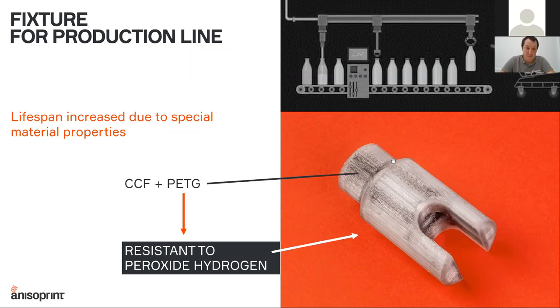For example, polyamides will start dissolving in hydrogen peroxide, and PETG is very highly resistant to this chemistry. By using PETG as a matrix together with a reinforcement to make the part strong and durable, the requirements are satisfied, and the part can work successfully for many hours at the production line.